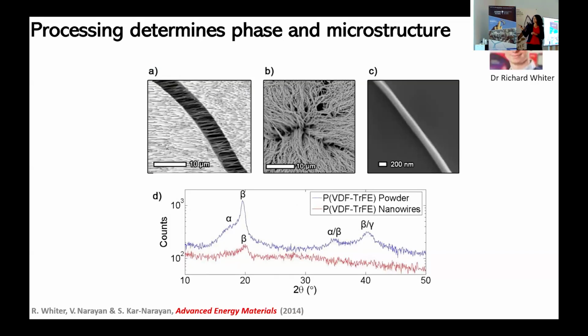And just to show you, this is actually my first PhD student, Richard Whiter, and we showed that by growing these nanowires, first off, there are some nice SEM images showing you what these nanowires look like in the crack. You can actually get rid of the template. You can dissolve it away to reveal just the nanowires, or you can isolate single ones to do more measurements. But the first surprise, really, this was serendipity, is that if you look at the X-ray diffraction spectrum,